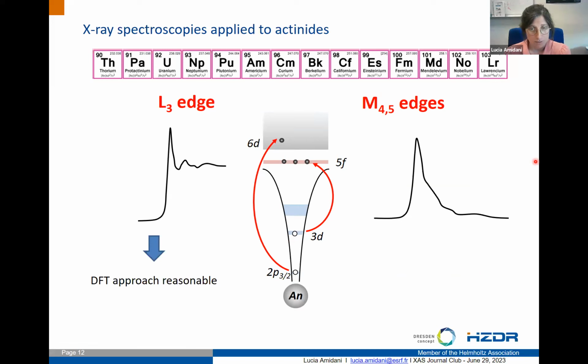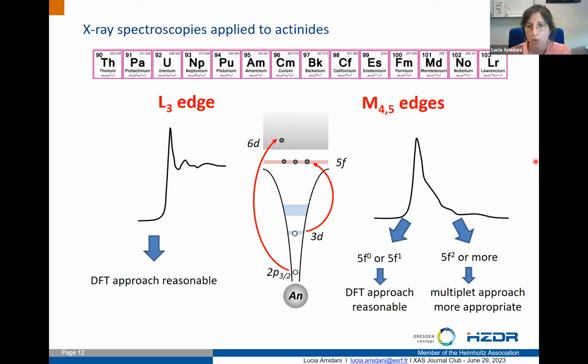What about the M edges? We might immediately say we have to go to another framework, but that's not completely true. In specific cases, for example where we have 5F0, an empty 5F shell, or maybe only one electron, the DFT approach is still reasonable, so why not try it? But as we fill the 5F shell more, those interactions become important and the multiplet approach becomes more appropriate. So this is indeed what we do.